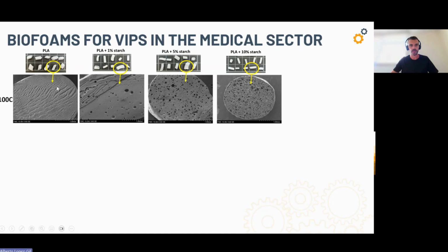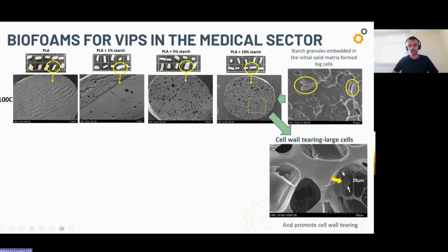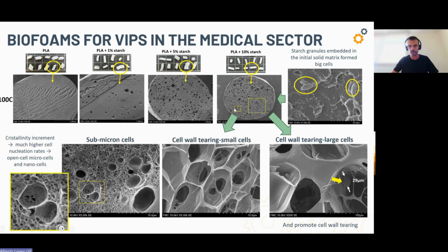These are the cellular structures of the foams we produce at 100 degrees. And as you can see here at this magnification, in the PLA foam without the starch, we barely see the cells in the microstructure because they are very small. We observe that as we increase the starch content, we have more bigger cells in the cellular structure. And this is because these big cells are formed around starch particles that are not completely embedded in the solid matrix. But we also observe in between the big cells that there are very tiny cells, which are submicron cells or even nanocells, which are still open.